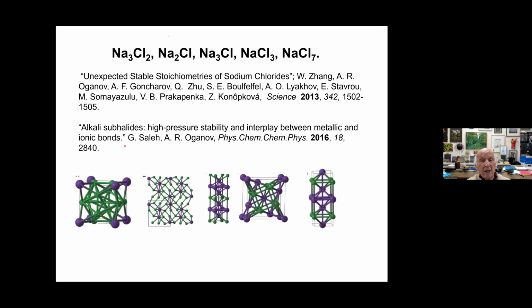Remarkable things. You get unusual stoichiometry. And this is also something where you can tell a difference between chemists and physicists. It turns out that you can take a mixture of sodium chloride, rock salt, and chlorine gas, and you subject it to pressure, and people have found from different mixtures the compositions which you see at the top. Don't pay any attention to the structures here. Just look at the compositions. You can get Na3Cl and you can get NaCl3.